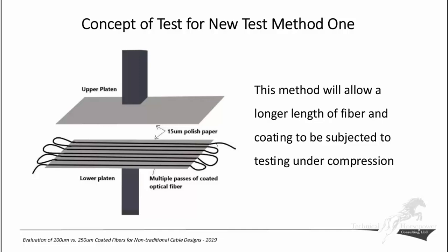So we wanted a longer gauge length and a surface that mimics the coated strength member's roughness, probably giving it a worse-case scenario than you would see in an actual cable design. But the idea of the test is to see what we can do to damage or mechanically abrade the fibers. So in doing so, we chose 3 sizes that we thought would be popular, 15, 25, and 50 microns, to do the test. And with the 24 passes in there, we felt we had enough gauge length to actually see a result.